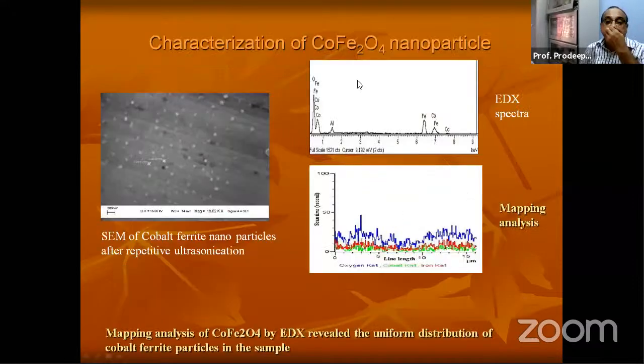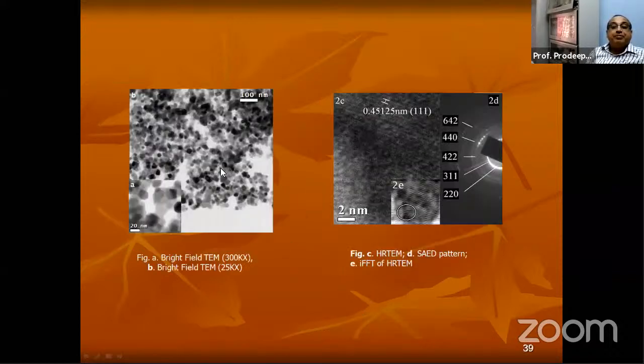So this is a characterization. This is the first characterization we did in 2009-10. This is actually the same picture. You see the particles, and this is the EDX spectra, and this is the mapping analysis. It reveals the uniform distribution of the cobalt ferrite particles in the sample. And this is a TEM picture.